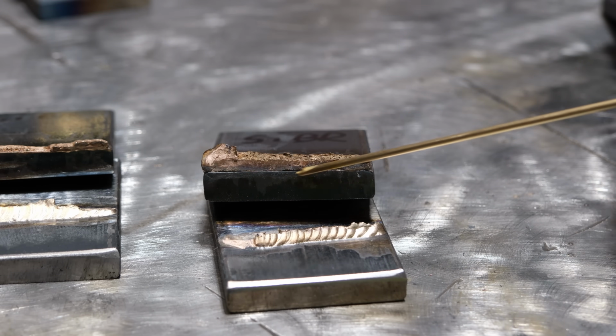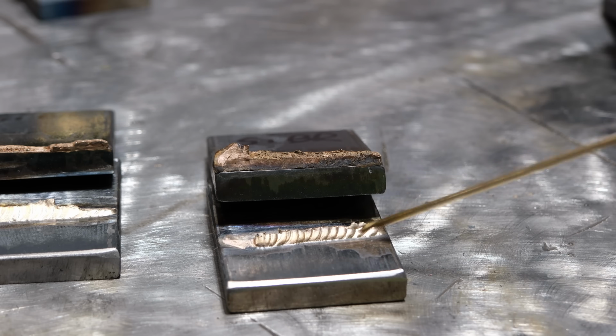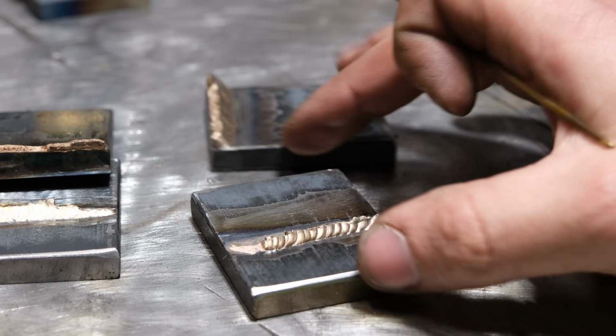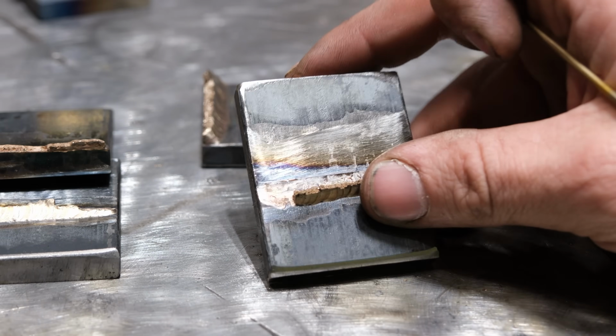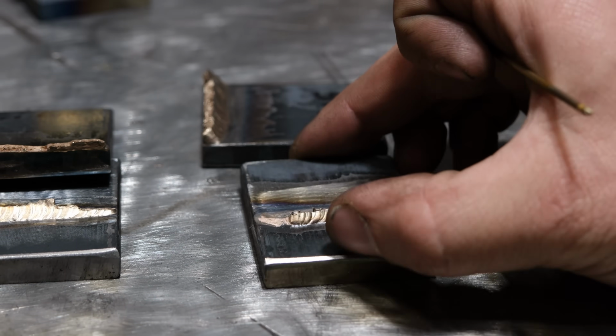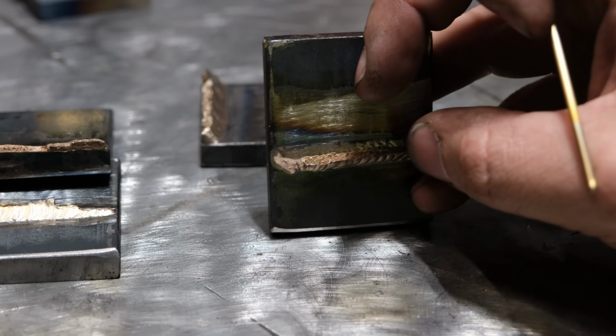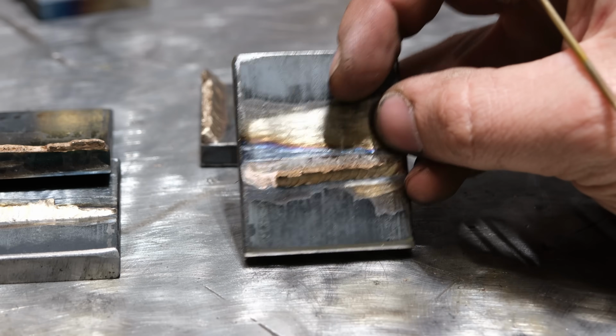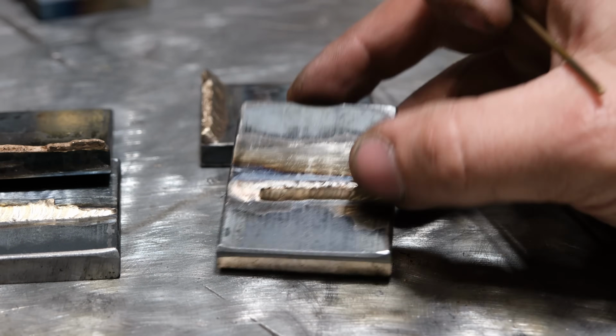Now, once again, the root pass of this is good. There is no melting of the base material whatsoever, and the braze itself failed. However, again, I think it was pre-cracked. It looks like it may have pulled a little bit of material off the base plate. Hard to tell.